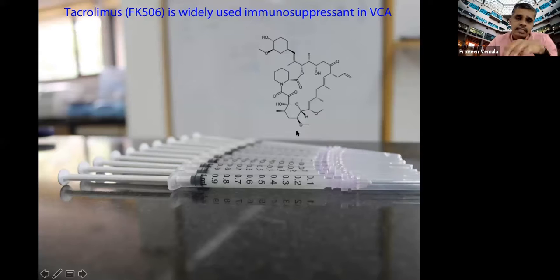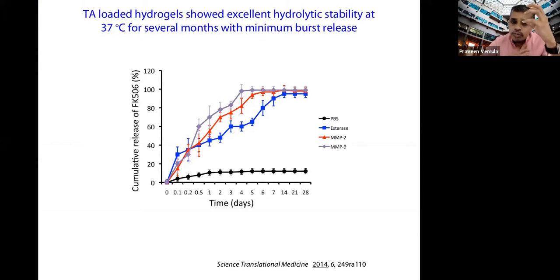Then once we had these gels, we tested their ability to release the drug in response to the proteolytic enzymes. As you can see here, in the absence of any proteolytic enzymes, you don't see any release of the drug. We have non-specific 5 to 10% of the drug release, but it stabilizes. We tested even after 90 days, like 3 months, and we don't see any non-specific release. But in the presence of enzymes, you can see nicely they degrade and release the drug. These are nicely stabilized in vitro enzymes, right?